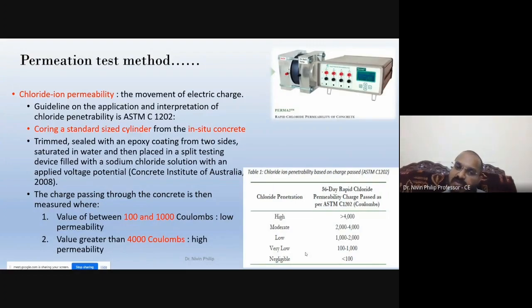So normally, based on this ratio, there is some summation equation. Based on the summation value over the 6 hour duration, we take a reading at around 30-minute intervals, and up to 6 hours we finalize the value. Based on that, we calculate the charge passed, and from that we can tell whether the sample we have taken is good or bad for chloride.